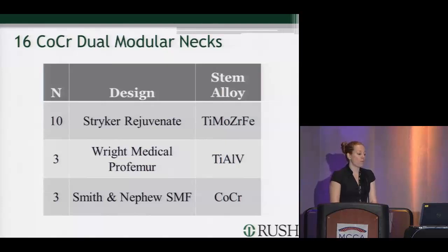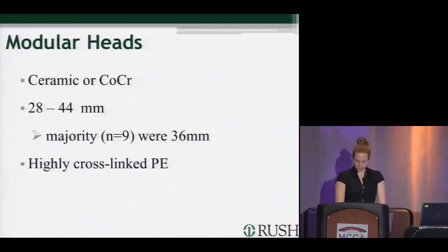16 cobalt chrome dual modular necks were studied. These 16 cobalt chromes came from 3 different designs. 2 of these designs employed a titanium stem alloy, and the 3rd design employed a cobalt chrome stem alloy. The modular heads that were coupled with these necks were either ceramic or cobalt chrome. They ranged in size from 28 to 44 millimeters, with the majority of them being 36 millimeters, and they all articulated on highly cross-linked polyethylene.